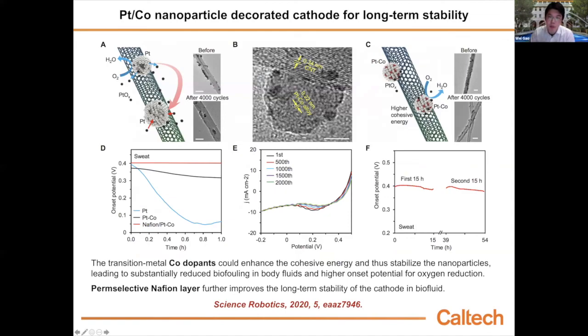This platinum cobalt nanoparticle can dramatically enhance the stability of this biofuel cell in the biofluids. Typically, with a platinum electrode, within 1 hour you see the performance decrease a lot. But our platinum cobalt based electrode can last much longer. If you coat it with a Nafion layer, it can remain stable over a very long time. Here is a 15-hour test followed by 24-hour storage. There is another 15-hour test. You see the performance is nearly the same.